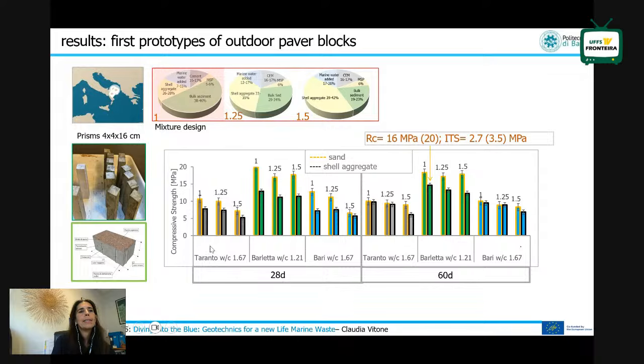We mixed these sediments following specific mix design and changing also the ratios between the dry aggregate and the sand, essentially the shell aggregate and the cement. And as you can see here, if we have the yellow contour, we have sand. If we have the black contour, we have shell aggregate. Essentially, sand is working better. But if we wait for longer curing time, so 60 days, you can see, for example, that this mixture